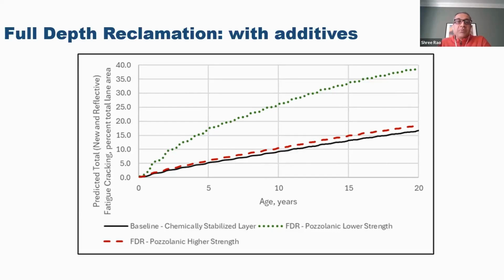So the total, which is the new and reflective fatigue cracking, here's the baseline case. This is the chemically stabilized example. So when you have the chemically stabilized layer, we have some reflection cracking and some fatigue cracking. And so that total cracking for the baseline case is lower when you have a lower strength cementitious material. You have a higher level of cracking, and then if you have a higher strength cementitious material, you can match the baseline cement stabilized layer design.